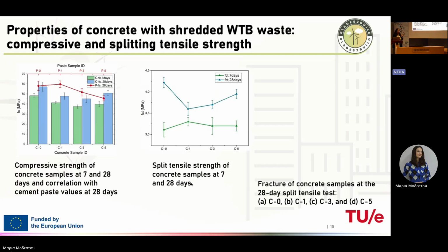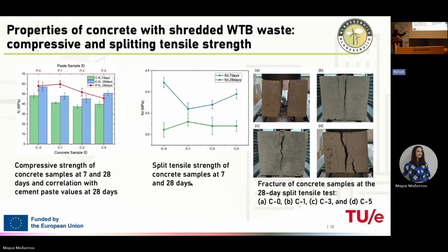For splitting tensile strength, since we have this effect of bridging cracks and some reinforcement effect, we see an increase of strength, especially at early age, 7 days. This is the green line. And at 28 days, we have some decrease, but for the 5% dosage of wind turbine blade waste, due to its reinforcement effect, we have quite nice results comparable to the control sample. And here is a test fracture of the concrete samples at 28 days of splitting tensile test in our structural engineering lab. So you can see this crack in the middle.